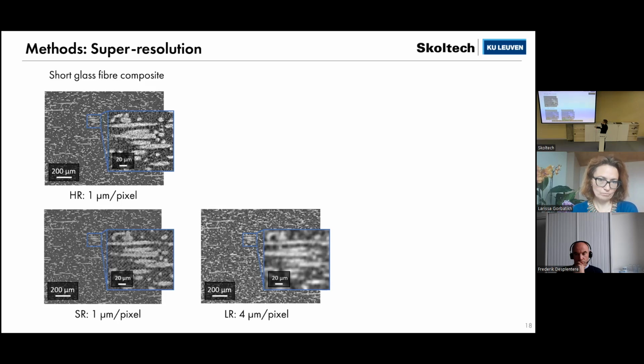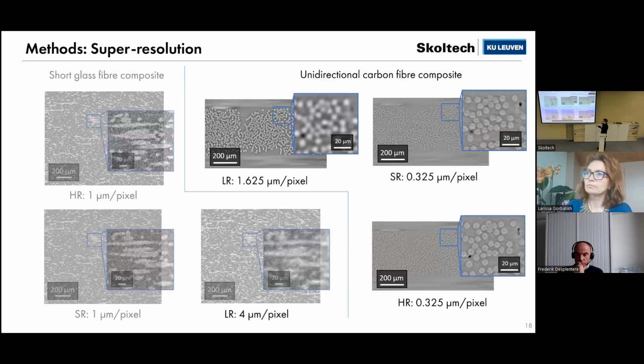And also you probably can see the texture of the enhanced images. This texture is due to the fact that we use convolutional operations, and in my opinion, it also can be removed by fine-tuning the model. But in our case, it's already a good result, and we can analyze it. And these texture artifacts don't give us problems later.